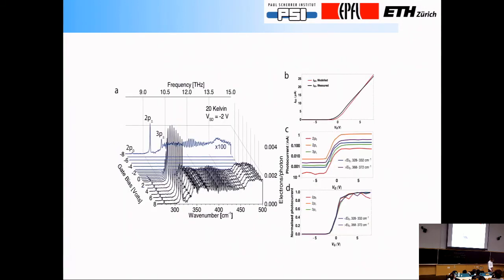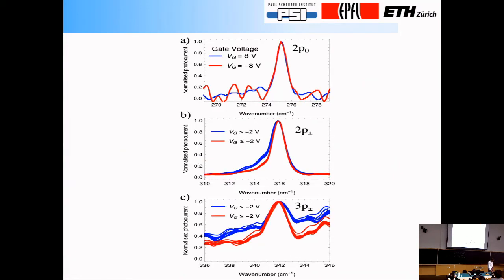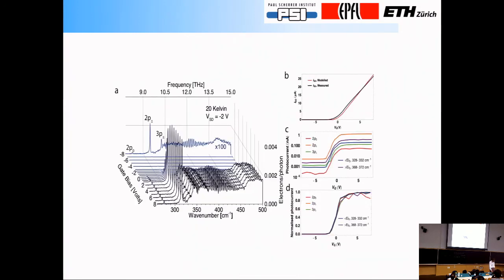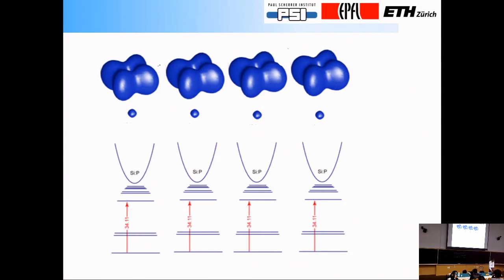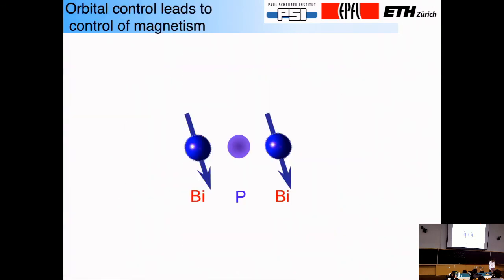And in fact, we've started doing some of that physics. We've actually done some photoconductivity measurements where we look at these Rydberg states where we change the gate voltage. In other words, we put them in contact with an electron reservoir, and we're finding very funny-looking line shapes as we go through the metal insulator transition, in that case, by adding electrons through a gate. I don't want to go into the detail of that, but the point is that the physics that's encapsulated in this cartoon is well alive and progressing.